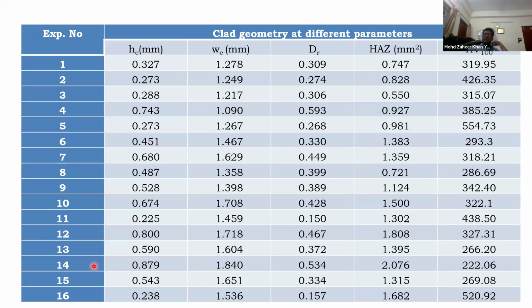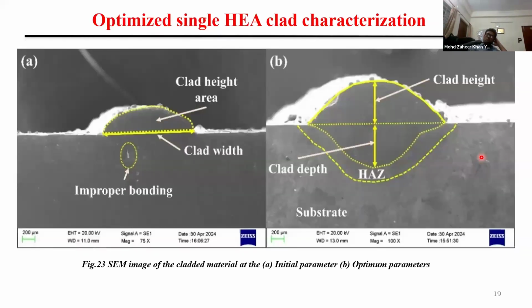So at different process parameters, different values of clad height, clad width, and heat affected zone are obtained, and clad height and clad width basically dictate the extent of dilution that we are obtaining in this particular case, and consequently this is reflected in the change in hardness of the material. So I'm just ending this part with this, that if proper bonding is not there, proper melting is not there, this type of problem may occur. Whereas if the process parameters have been optimized, then this type of clad layer is obtained, and subsequently several such clad layers can be deposited to cover the substrate material with the clad.